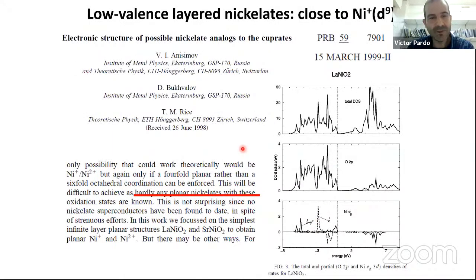One possibly better way would be to go to lanthanum nickel O2. And this has been considered for more than 20 years already. Anisimov was one of the first in doing calculations in lanthanum nickel O2. Lanthanum nickel O2 would be nickel plus, would be the exact same nominal filling of the d band as in the cuprates.